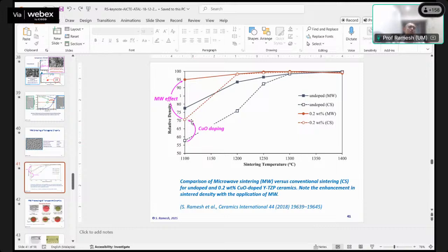All right. Now, when he used the same material, that formulation with copper oxide doping, when he coupled it with microwave, at 1100 coupled with microwave for 1 minute, we can reach 95% dense. All right. So as you can see, microwave has that ability to increase or enhance densification of zirconia at a very low temperature of 1100 and within a very short period of time.